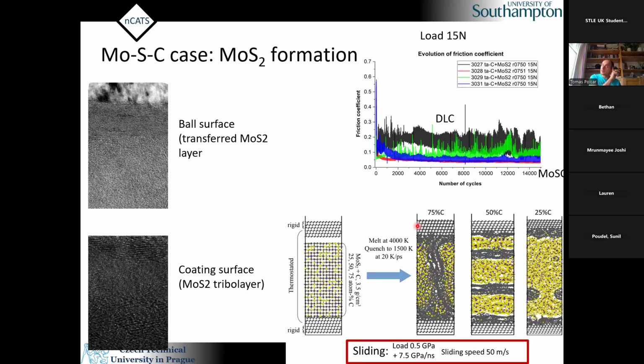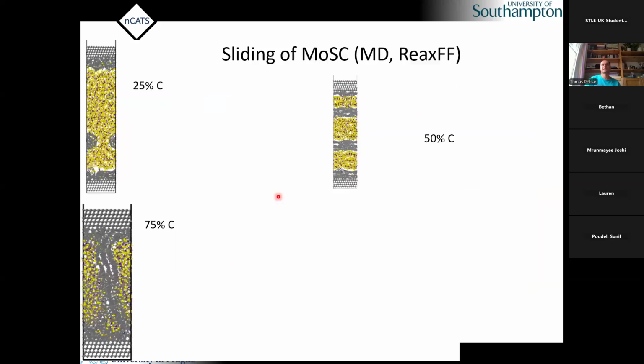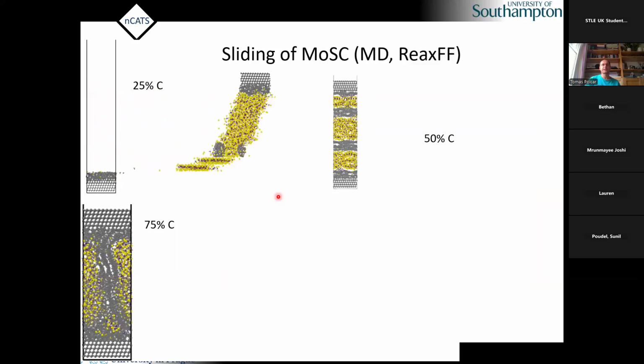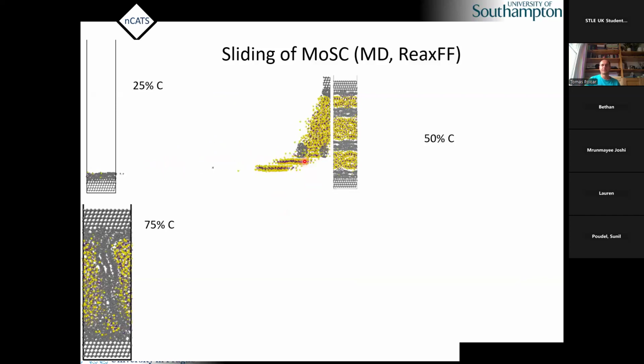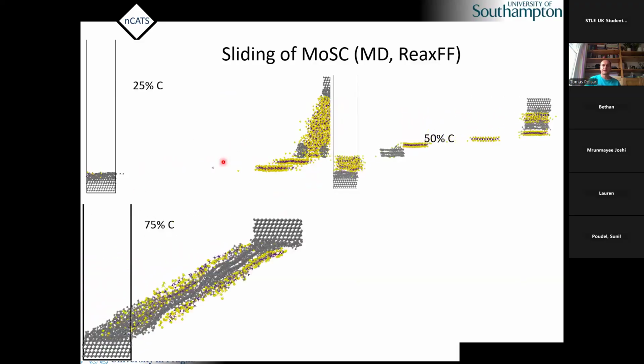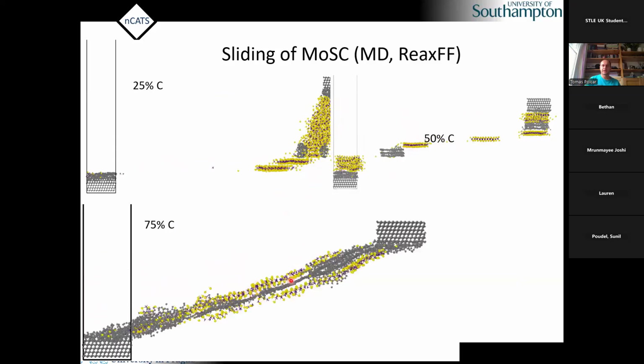And then I went back and we did some simulation. Again, I will show it very briefly, without much explanation, what is possible now, just to demonstrate. So we have some experiment. This is the friction coefficient measured. Then we can see that there is some tribolayer formed. And then we can do some simulation and try to predict that. You will see this in this video. So you see that we have a simulation. It shows here that we form this very nicely aligned tribolayer. And even when we change some parameters, we still form it here, or even there. You see it start to form.